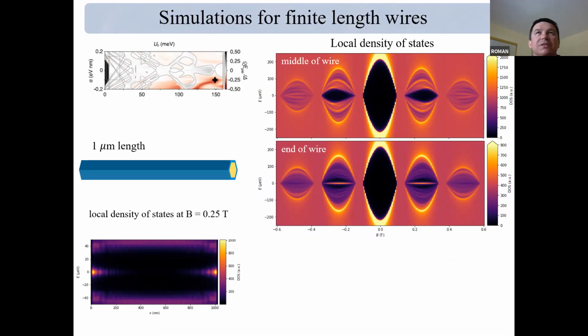So if we have, say, a flux line in a superconductor, and you don't have spin orbit coupling, then there is no way the motion in, say, radial coordinates and z coordinates decouples, and there is no way to get localized states in the z direction. You will get quantized states in the radial direction, but it's going to be basically a gapless mode along the direction of the wire. So that's an interesting effect of spin orbit coupling, that it couples radial and longitudinal directions and leads to these localized end states.